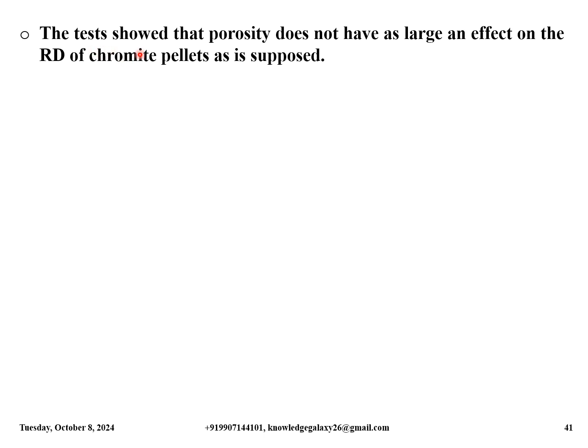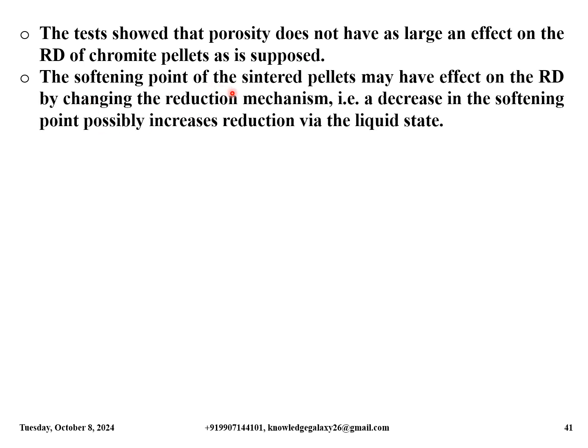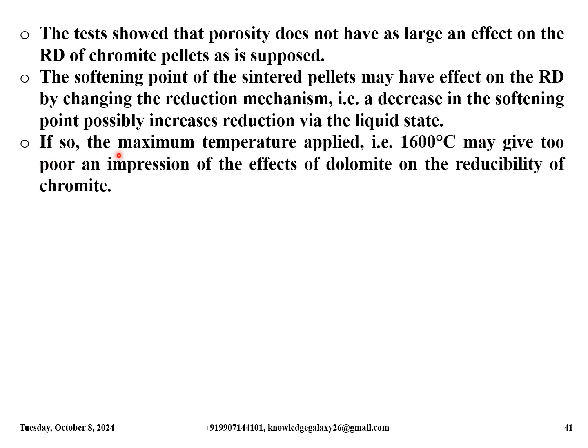The test showed that porosity does not have as large an effect on the reduction degree of chromite pellets as is supposed. The softening point of the sintered pellets may have an effect on the reduction degree by changing the reduction mechanism, that is, a decrease in the softening point possibly increases reduction via the liquid state. If so, the maximum temperature applied, that is 1600 degrees Celsius, may give too poor an impression of the effects of dolomite on the reducibility of chromite.